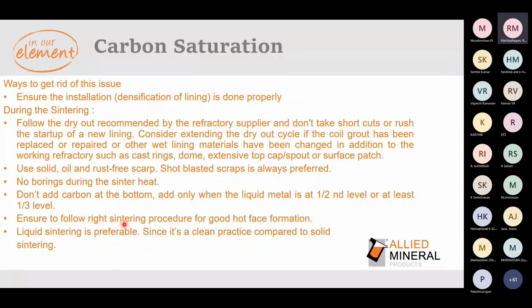Coming to the solution, how to eliminate this issue. We need to first ensure a proper installation, that is densification of the lining and hot face formation, following the right procedures for the sintering. And make sure that the grout has been dried out, and the other structural components like bottom blocks and top blocks are dried completely, because all these contain moisture. When the furnace is new, there's a lot of possibility that more moisture is there in the system. So make sure a proper dry out cycle is followed to eliminate all this moisture before the lining is started.